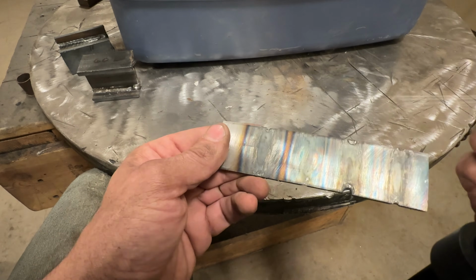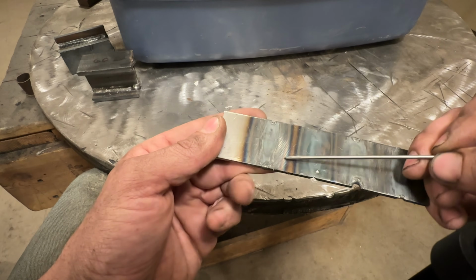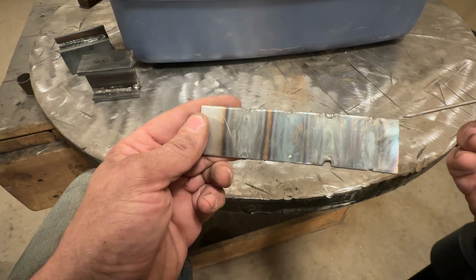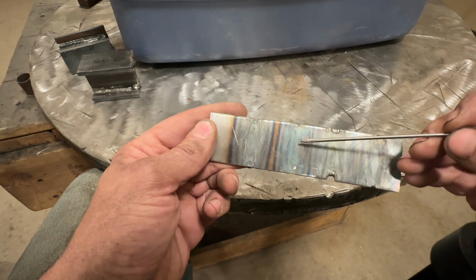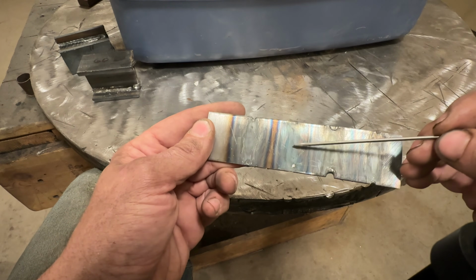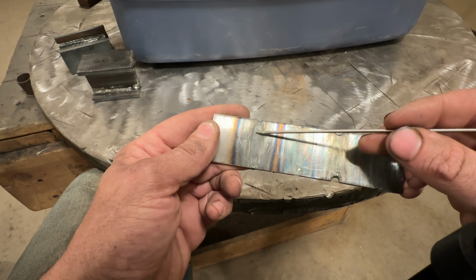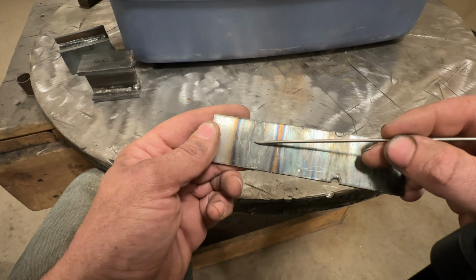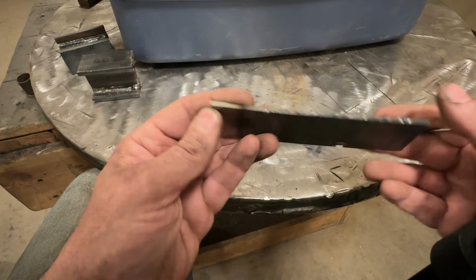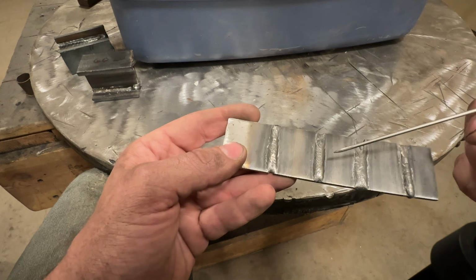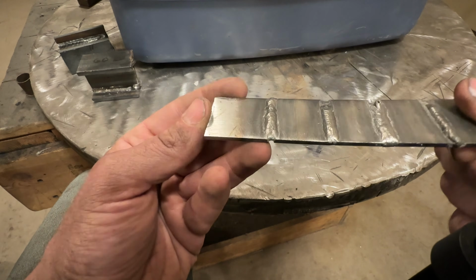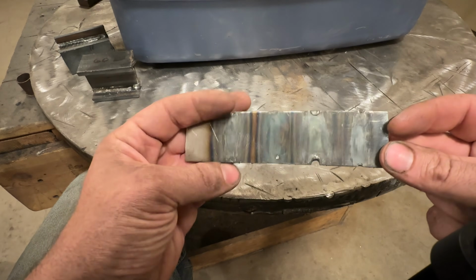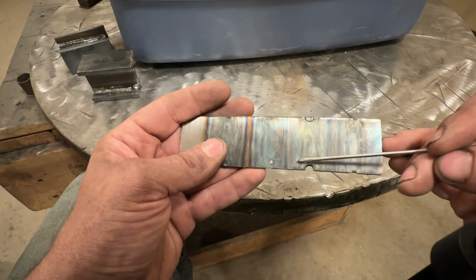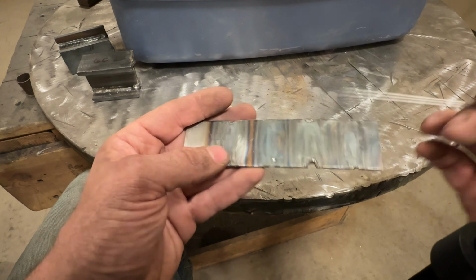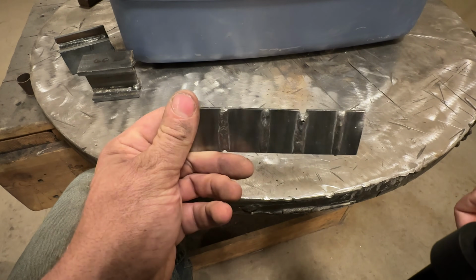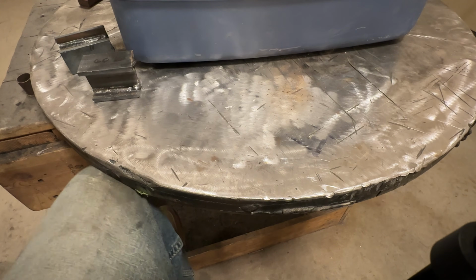Don't be afraid either, on clean material, if you see your heat affected lines like this, they tell you a ton. You look at how close the heat affected zone is on this weld, and that's going to tell me that this is a colder weld than this, because if you split the weld down the middle and measure the distance, it's further than this. So that's telling us that this was run hotter potentially than this. On this side they look fairly similar, but you get the idea. Over here, there's no question. The heat affected zone is way wide on that, and much like you would expect, it blew it out.